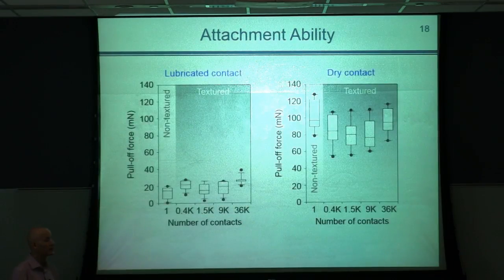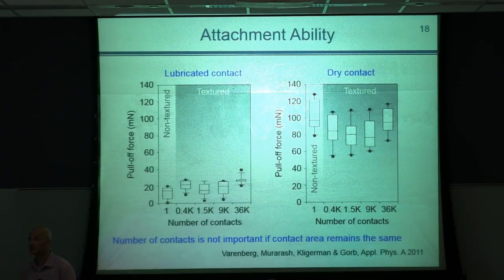So first of all, we tested the attachment ability in order to verify this contact splitting principle, and it appears that the idea is wrong. So what you see here are pull-off forces represented as a function of number of contacts.